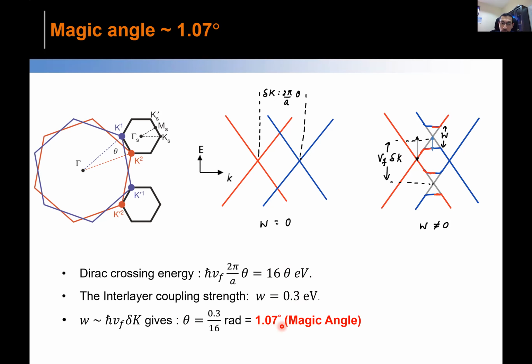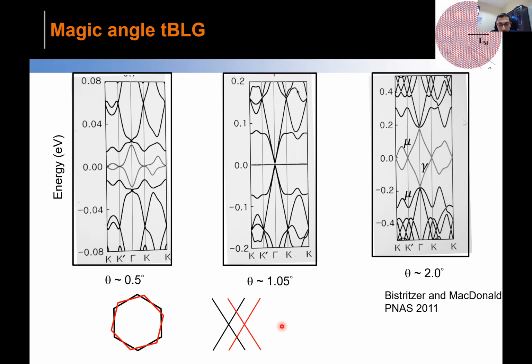So, such a crude way, but this gives almost close to the magic angle, 1.07. Having said that, people have done this. This field started because of MacDonald and this paper in PNAS 2011. They calculated the energy versus momentum relations for different angles of this twisted bilayer system. And what they could see is that if you go to 0.5 degree, the dispersion looks like this.